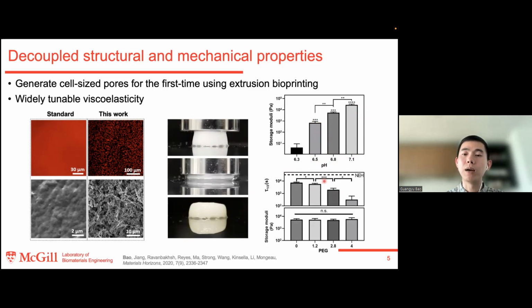And by maintaining the pH at a similar level, and simply by changing the PEG concentration within the original bioink, we can maintain the storage modulus the same, but orthogonally tune the viscoelastic response. Here, we tune the stress relaxation time from thousands of seconds to tens of seconds, which also covers a wide range.